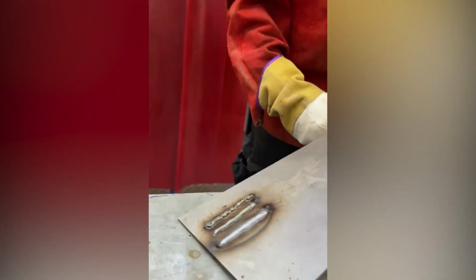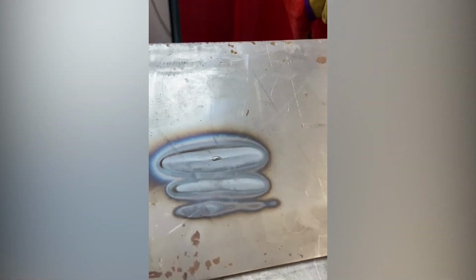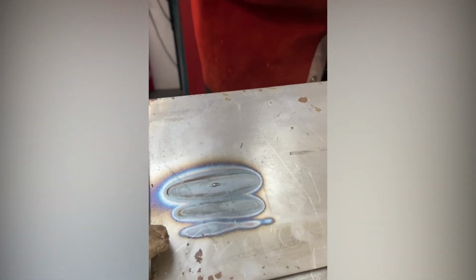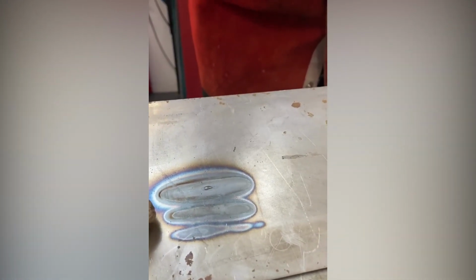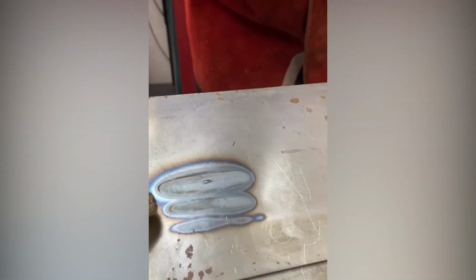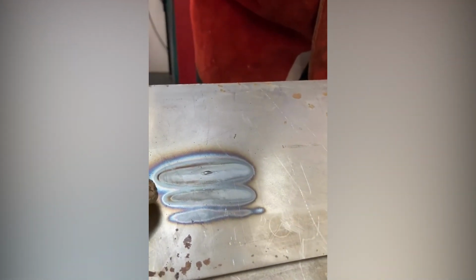we should see the levels of penetration. With no gas, very little penetration. When the power setting was too low, again, it's not quite good enough.